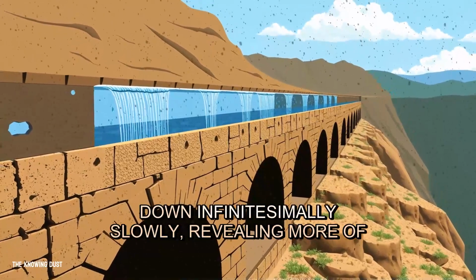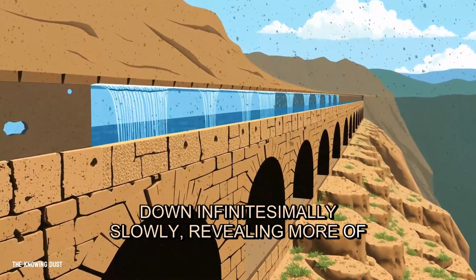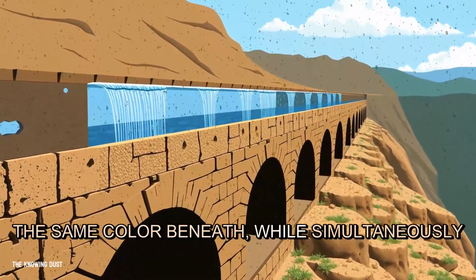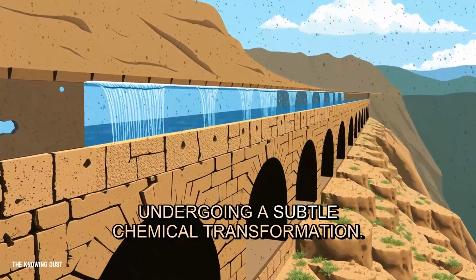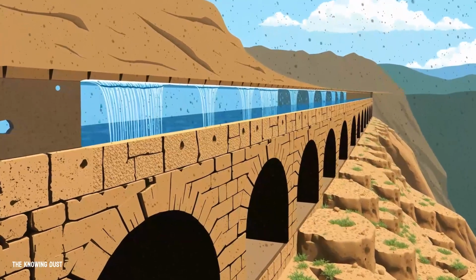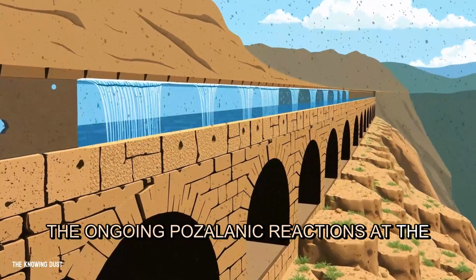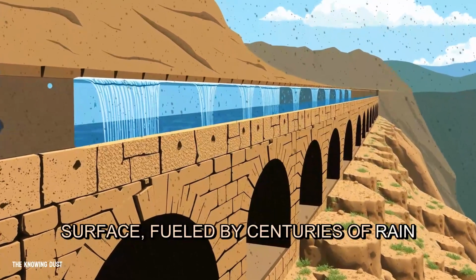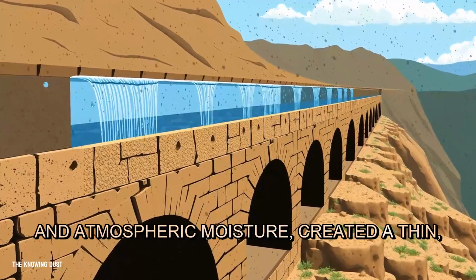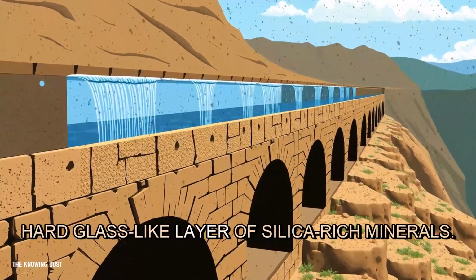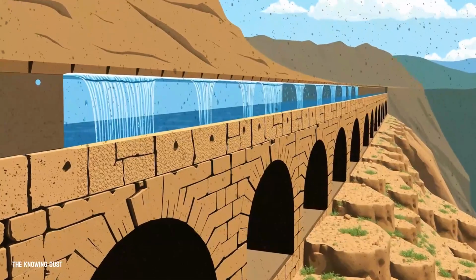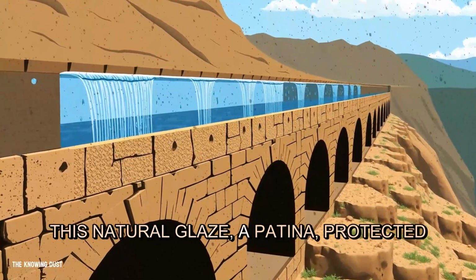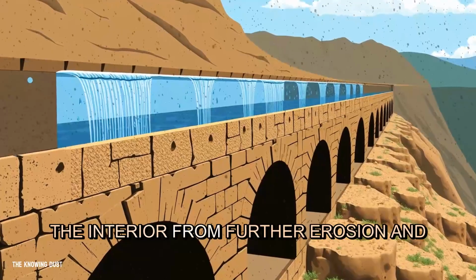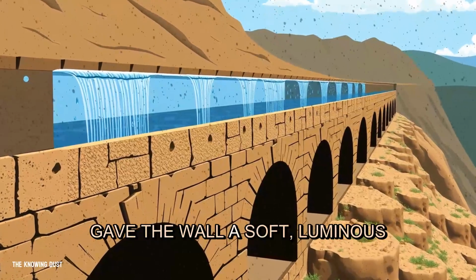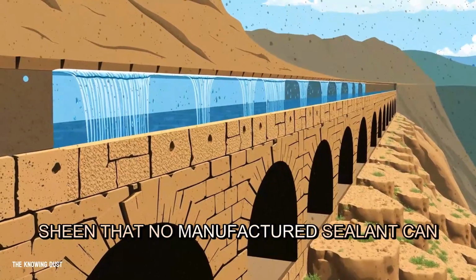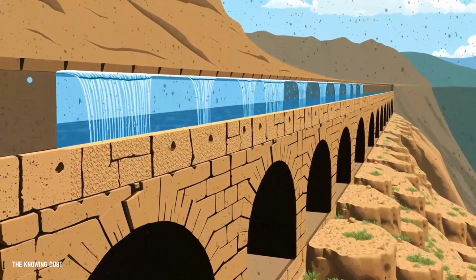It wore down infinitesimally slowly, revealing more of the same color beneath, while simultaneously undergoing a subtle chemical transformation. The ongoing pozzolanic reactions at the surface, fueled by centuries of rain and atmospheric moisture, created a thin, hard, glass-like layer of silica-rich minerals. This natural glaze, a patina, protected the interior from further erosion and gave the wall a soft, luminous sheen that no manufactured sealant can replicate.